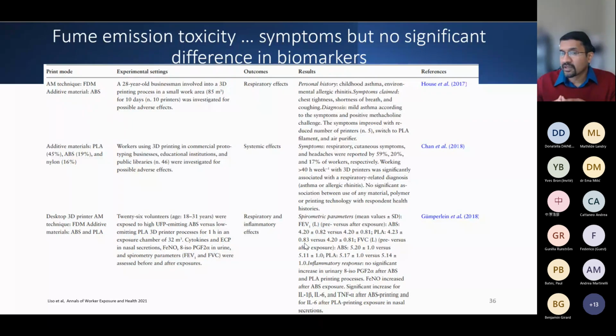Exhaled nitric oxide was somewhat increased after the ABS exposure. So this was a unique example, which I find fascinating, where they actually were able to test emission chamber studies with healthy human volunteers and be able to evaluate it. However, work that has been done prior to that talks about symptomatic increase that was witnessed in, I'd say, what is common use environments, whether it be educational institution or you may be doing with smaller systems. So symptomatic response, yes, but definitely no significant difference in biomarkers.